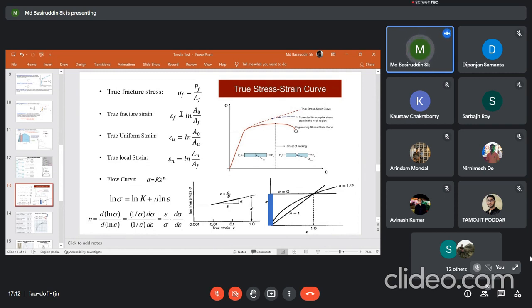But whenever you do this sort of calculation, please keep in mind that when we convert the engineering stress to true stress, up to the UTS the gauge length is important. Because throughout the gauge length the deformation will generally happen, and that is why just by knowing the engineering stress, you can directly convert the engineering stress to true stress as well as the true strain. But beyond the UTS, beyond the ultimate tensile strain, you have to continuously measure the reduced cross-sectional area.